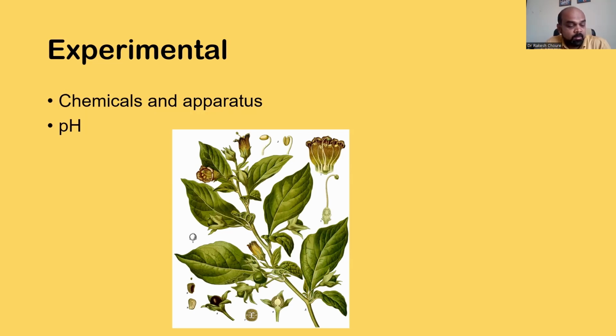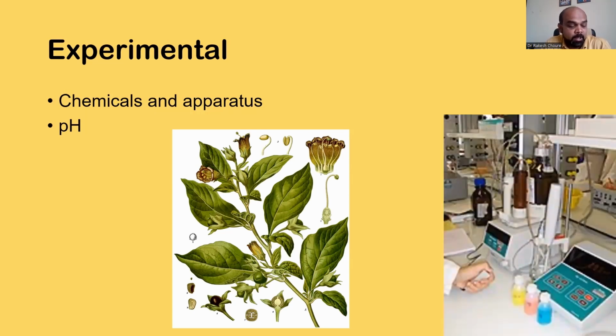Experimental set was prepared by taking 1 ml of sample solution and 10 ml of borate buffer as supporting electrolyte in a polarographic cell. The total volume was made up to 50 ml with distilled water. The pH of the test solution was adjusted to 8.2 plus minus 0.1. So here in this picture, you can see the polarograph.